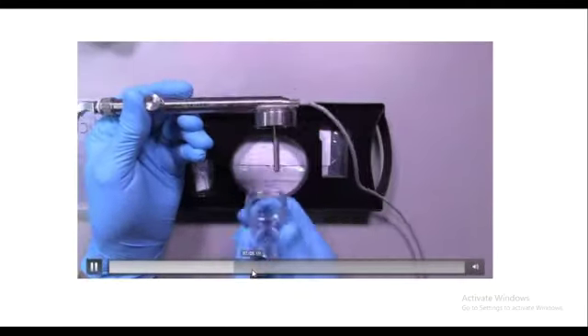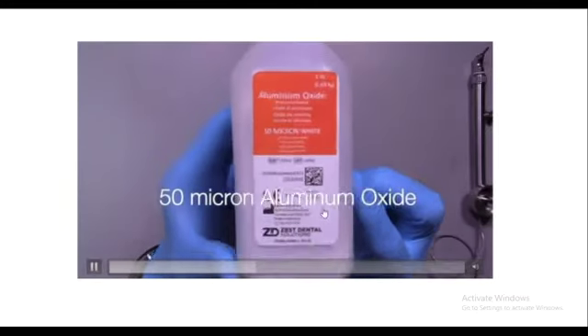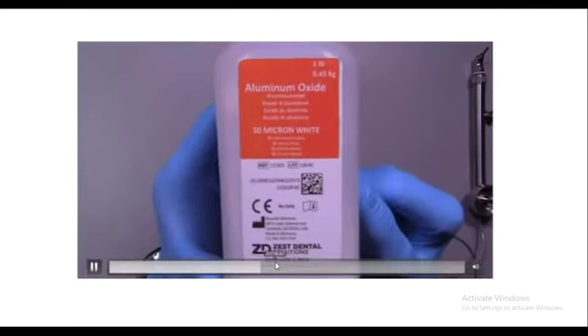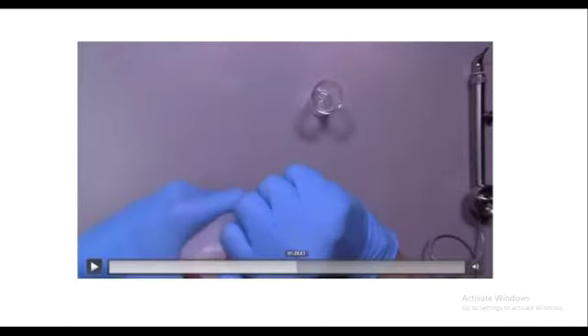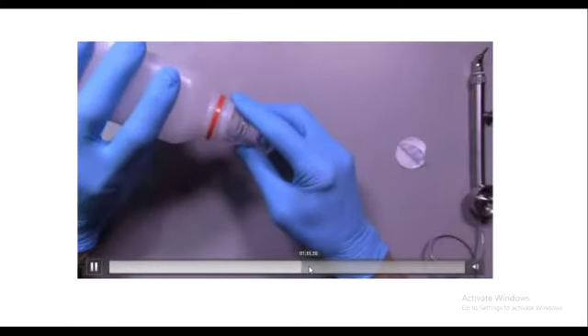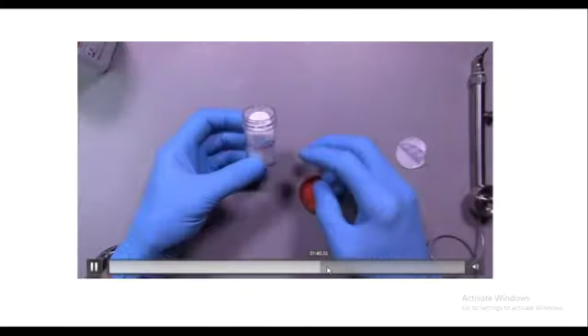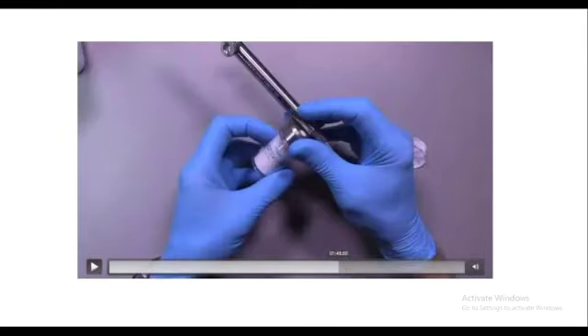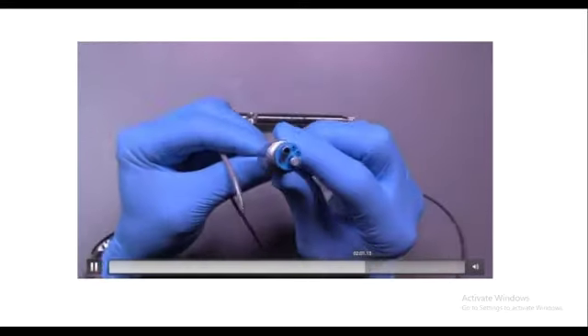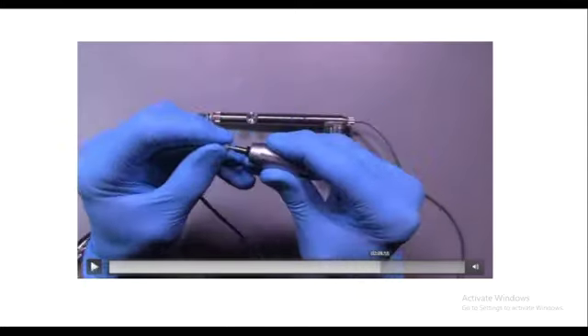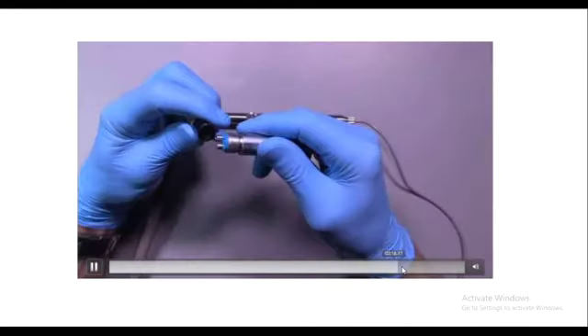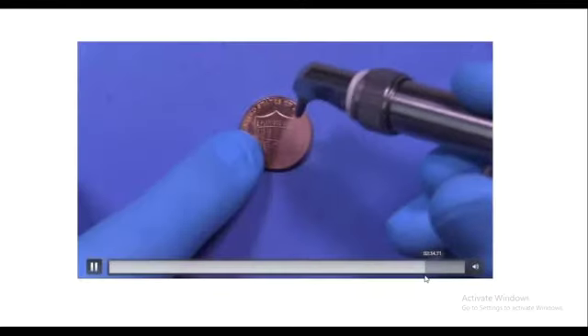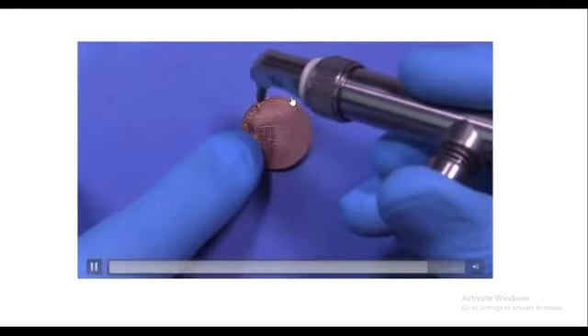I happen to like using the 7 micron aluminum oxide. This is the 50 micron alumina, which is kept in the small container. For the technique, we need to lightly sandblast. You can purchase a little adapter that allows you to connect it and just put it on the bracket table for use. So I'm going to sandblast the surface, and you can see that the thing that's kind of cool about this is that there's just not a lot of debris.